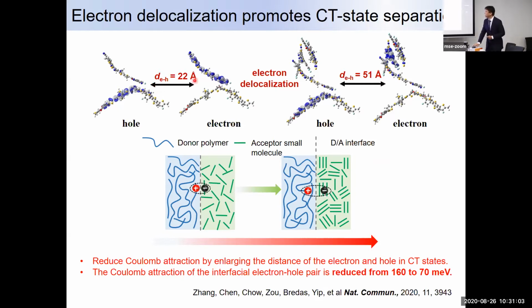However, now if we have a very good packing or aggregate of this acceptor material at this donor acceptor interface, you can see the exciton distance actually is extended to about 5 nanometer. Okay, so if it is extended, which means the Coulombic interaction attraction at the interface is reducing. Okay, from the monomer is 160 meV. For this trimer of the acceptor, right, it is about 70 meV.